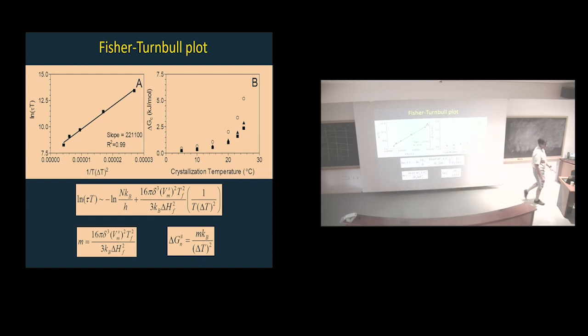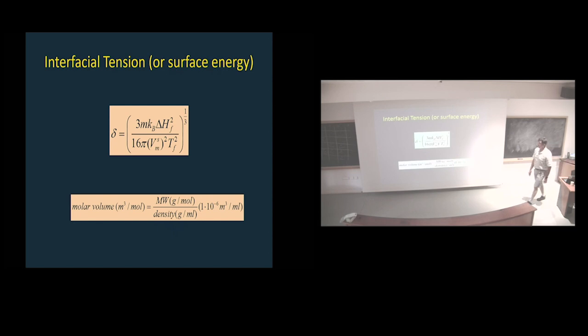Totally usable. And then you can get, this is one way of getting to that interfacial tension term by kinetic analysis. So you just do the cube root because it's in there, and you have the slope you determined for the Fisher-Turnbull plot, you have the enthalpy of melting from DSC, you have the density because you read it, and the temperature of fusion, and you can get that. We sort of believe it. But we've used it as an indicator. It's not 100%, but you go out there and try to determine the interfacial tension differently. It's not that difficult. And here's just the conversion between density and molar volume for you to use.